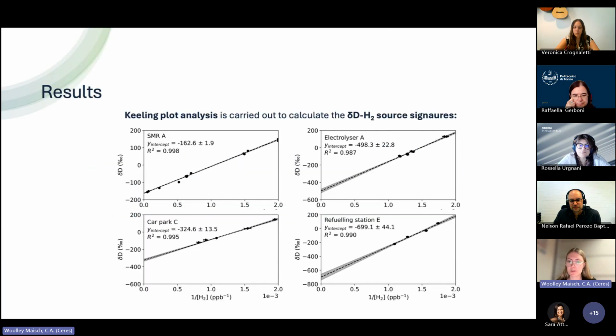So as I mentioned, we went to a lot of different sources, but we're not measuring pure hydrogen, we're measuring downwind of the source. In our sample, we have atmospheric hydrogen plus the source hydrogen. So to get the source signature, we need to get the value of the hydrogen addition on top of the background. And for that, we use the Keeling plot method. This is used a lot in the methane world. Basically you plot 1 over the mole fraction against the delta D, and then the y-intercept gives you the source signature, like what was shown in the figure from Gibson et al.